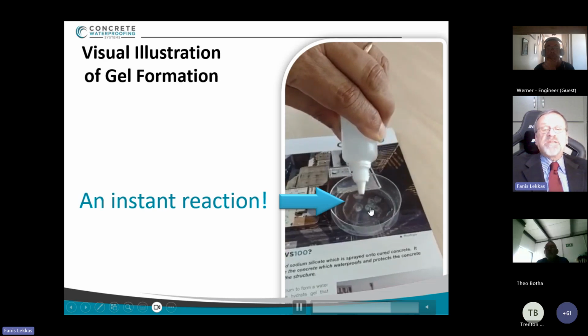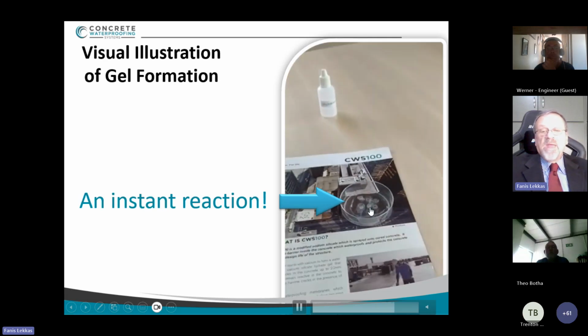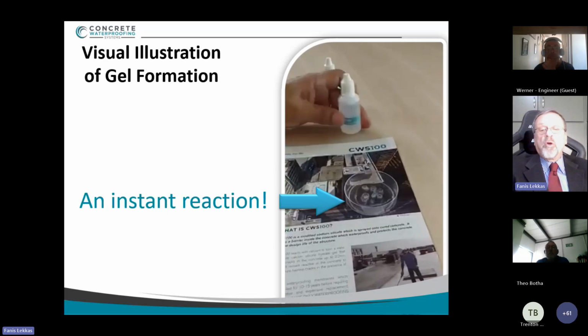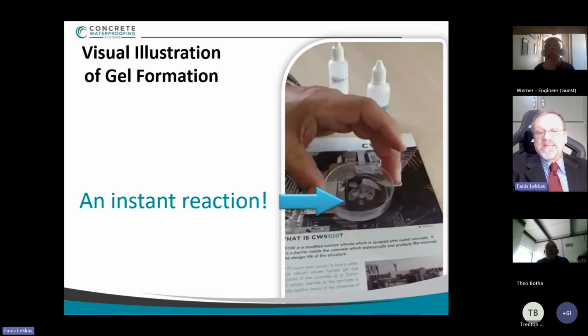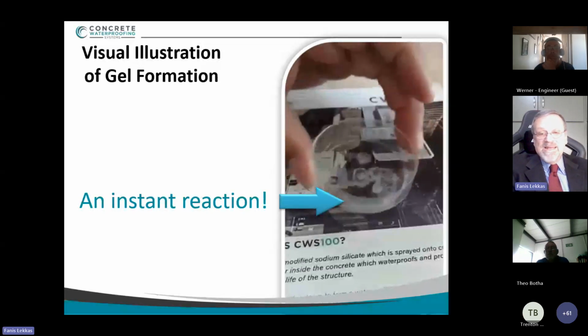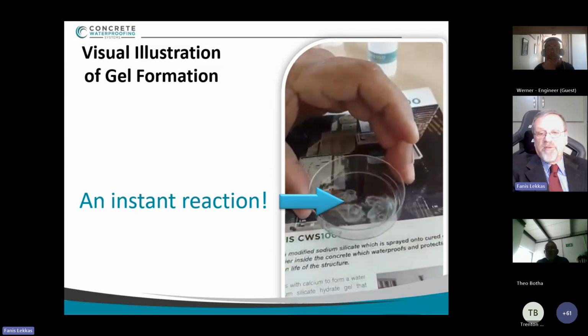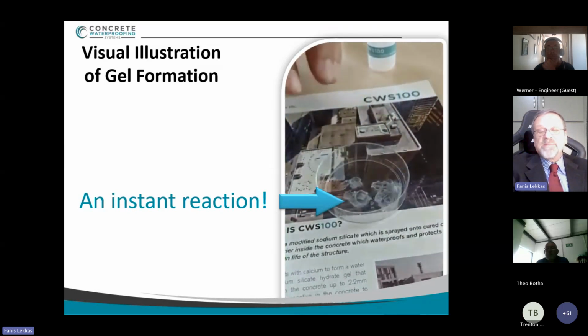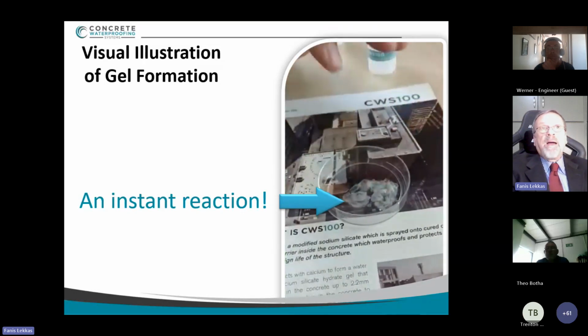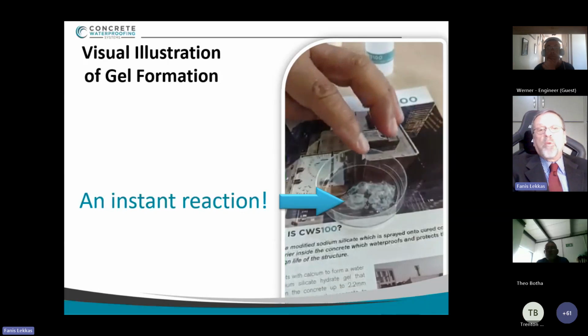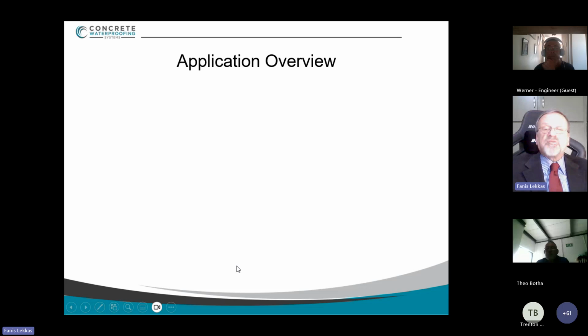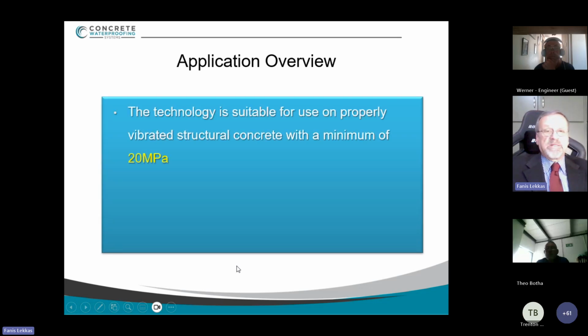The gel formation starts instantly, and the gel starts to grow 5, 6, 7 times its size. Look, in less than 10 seconds, 12, it grew 5, 6 times its size, absorbing all the available water. This material is not hydrophobic, it's not a water repellent. On the contrary, it is a highly hydrophilic material. It loves water. The more you give it, the better it is.